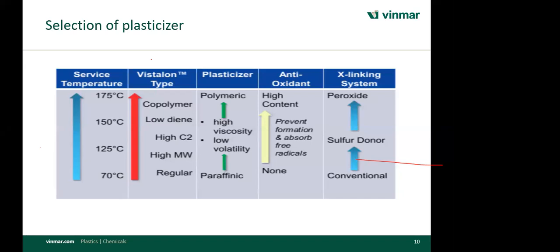But if you go for high heat resistance and peroxide cure, then paraffinic oil is recommended. Again, paraffinic oil has low volatility. And if you go for the high temperature range, then we recommend high viscosity paraffinic oil. And for the higher service temperature, we recommend polymeric plasticizer. Polymeric plasticizer is the ester type, like of sebacic acid or soybean oil.